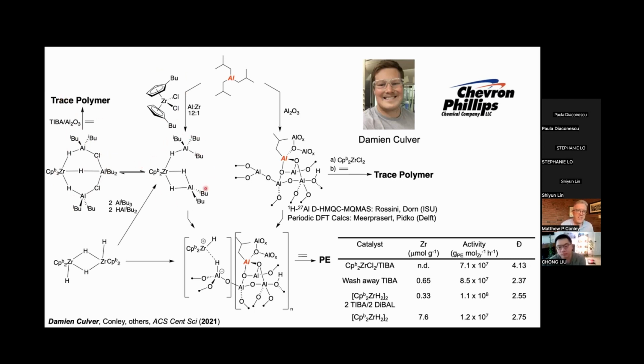If we take this hydride, which we can generate independently from a known dihydride dimer and appropriate amounts of organoaluminum compounds, we can make this in solution. We put it on TIBA alumina. It becomes very active in polymerization. If we take the dihydride without the exogenous alkyl aluminums, we generate this ion pair as well with a slightly higher loading of zirconium, which is what we then use to study in more detail. So knowing what we knew going into this, we assumed we had something like this, where we have this ion pair that would be prepared by hydride abstraction by a Lewis acidic aluminum, okay?